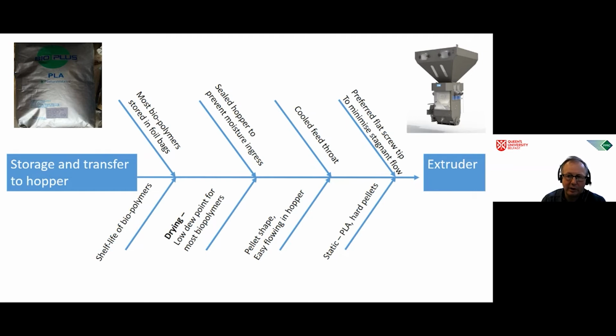The granules themselves can be very different in shape, and in particular, PLA is a very hard, incompressible pellet. So that must be considered when blending, whereas something like a TPS would be a much softer material. Also, in the design of the screw, if there are any areas within the extruder where material can be hung up, then this would potentially cause issues in terms of material degradation.